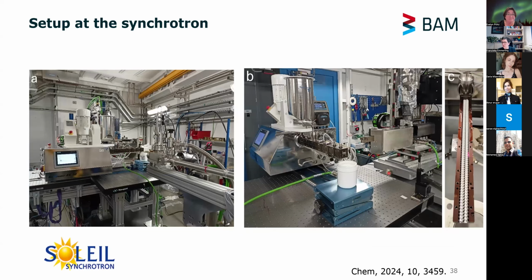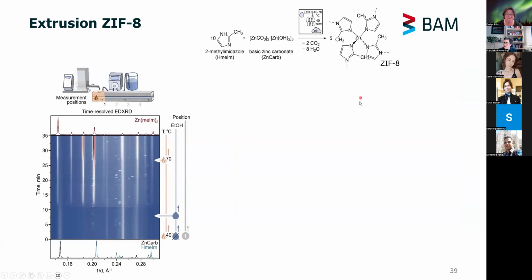Again, synchrotron. This one looks not so messy compared to the other picture, but it's at the beginning. It's not in the middle of it. And then you get information about these processes, and just to quickly show you that here, for instance, we used ethanol and heated one area. You can see we get a highly crystalline ZIF.